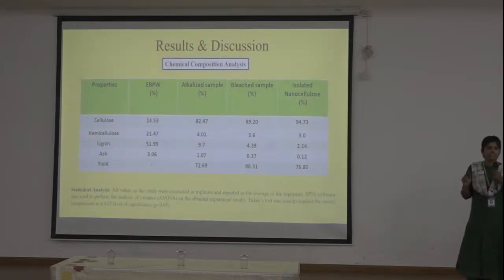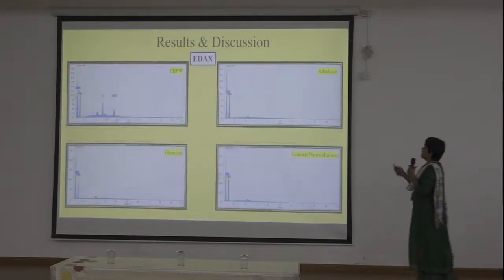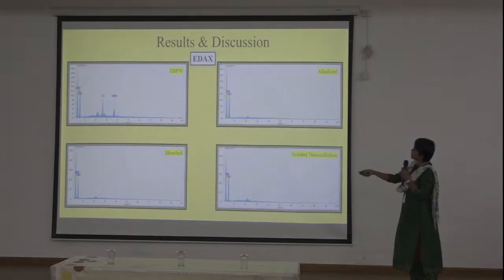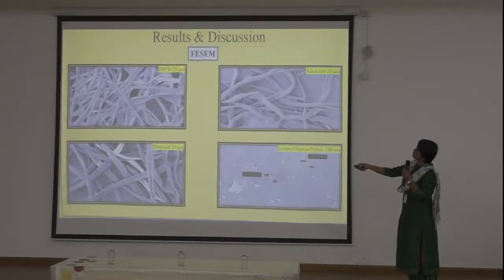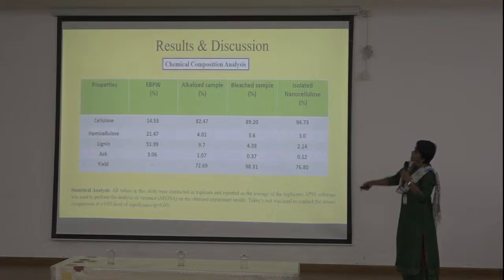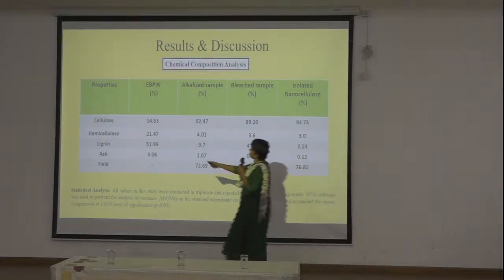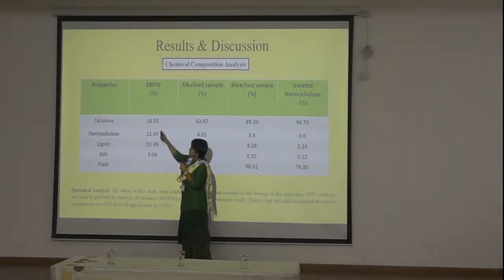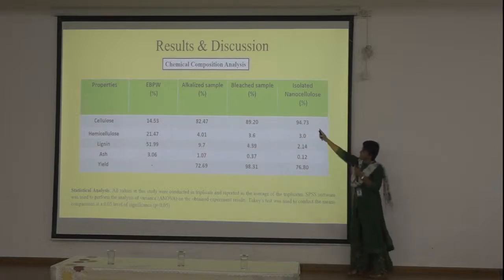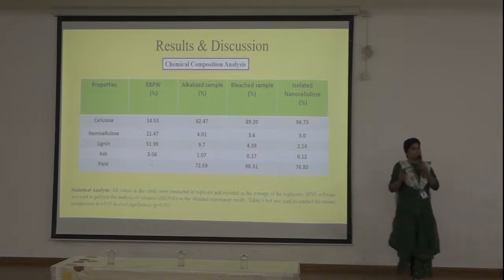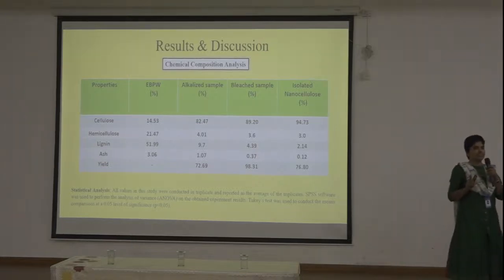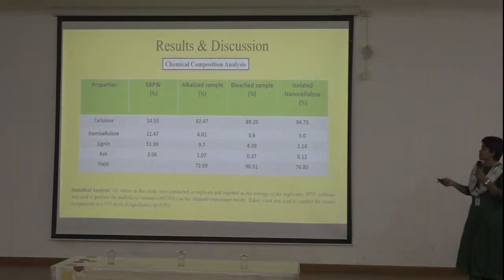Coming to results and discussion: here in embroidery backing paper waste, this was the amount of cellulose, hemicellulose, lignin and ash. After the treatment, there was 94% cellulose and the percent of hemicellulose and lignin was reduced. This confirms my treatment was very effective in isolating the cellulose.